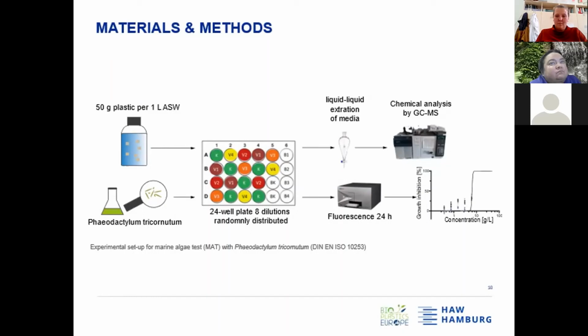And like for the leachates for the daphnids, the plastic materials were cut into small pieces and then put in the media and shaken for 14 days in the dark to avoid disintegration of the materials. Afterwards, the leachates were diluted by a two-step procedure until the lowest concentration of 1 to 128 was reached. And this is a concentration of 0.4 gram bioplastic per 1 liter medium. To avoid influences by external effects, like for example uneven light conditions during the test, the test concentrations or the leaching dilutants were distributed randomly on the well plates, which you can see there.